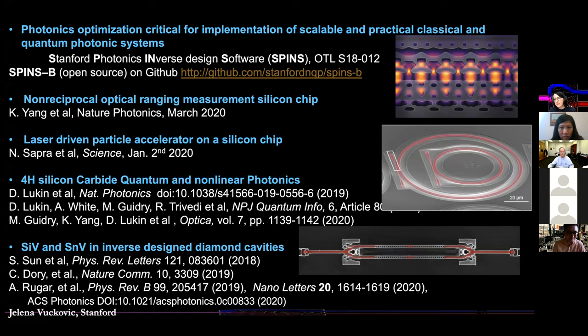The problem is that in the experiments that we did so far, we didn't use the highest quality quantum emitters. We used commercial material from Cree, and we generated silicon vacancy color centers by proton irradiation, basically just kicking out silicon atoms. That didn't really result in the highest quality color centers. So now we're collaborating with teams in Germany and Sweden on growth. First, high quality material in the right type of cut so that color centers have in-plane polarization, so they couple to the electric field. That was one of the problems in the previous work.